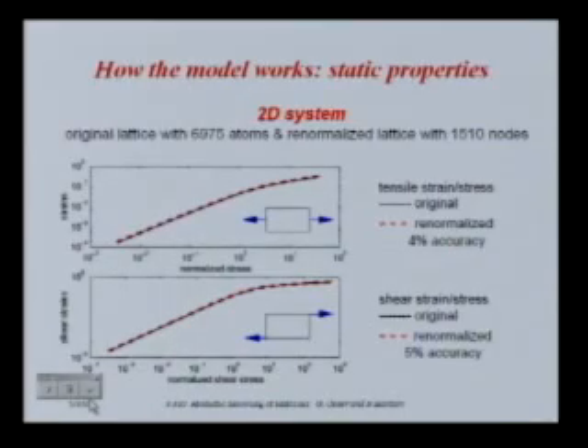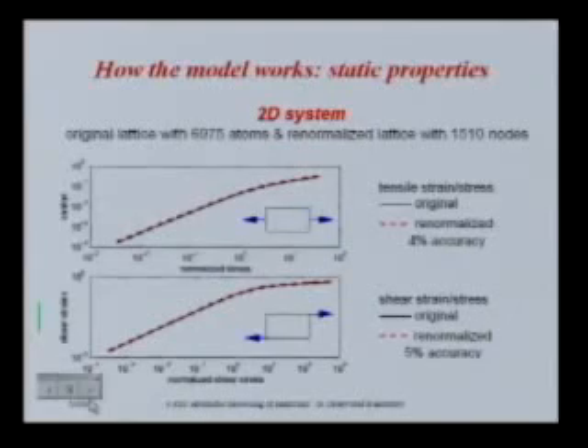So if you take a simple pair potential model, these coarse-graining schemes work pretty well. Here's essentially a static property, even though it has temperature in it—this is the strain in that 2D system versus the stress. The black curve underlying this is the full system, so no coarse-graining, and the red curve is the coarse-grained system that I showed you.